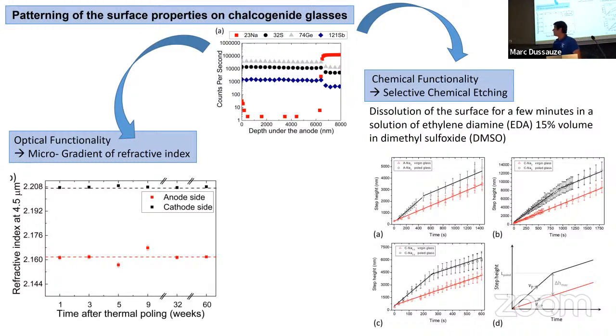reactivity. So we put this glass in a solvent of ethylenediamine in DMSO, and you can see here the dissolution rate of the glass, okay? So that's a pristine glass, it's linear. The more you put the glass inside the solvent, the more you remove mass, and that's linear. But if you have a poled glass with this first layer, you see that you have a first, let's say, much more rapid dissolution, and then something which is parallel. So in this zone, this graph depends on the glass compositions. In fact, you can see the change of dissolution rate. So you have a very different chemical reactivity after and before poling, induced by the change of composition.